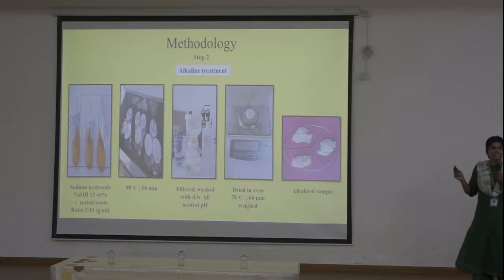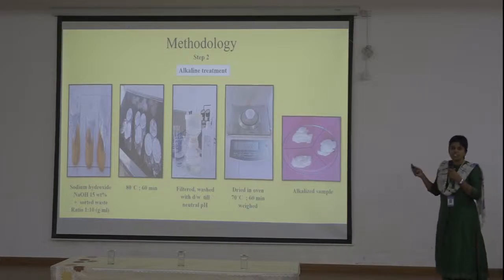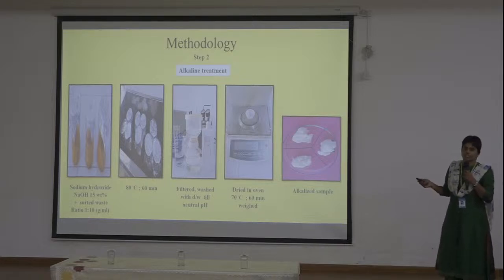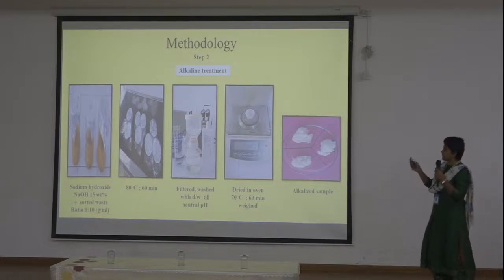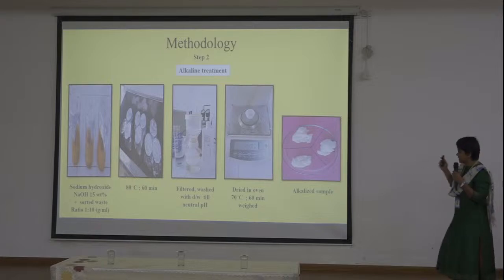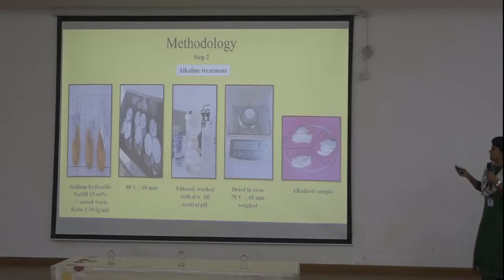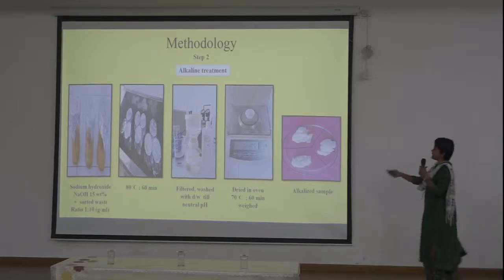Sodium hydroxide is the classical method to remove hemicellulose. The concentration, temperature and time for my entire experiment were optimized in laboratory conditions. After optimal treatment, the samples were washed and filtered for neutral pH, then dried in the oven and weighed for yield calculation. This is the alkali sample.